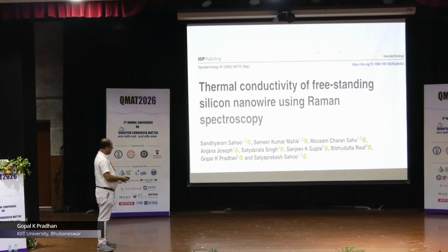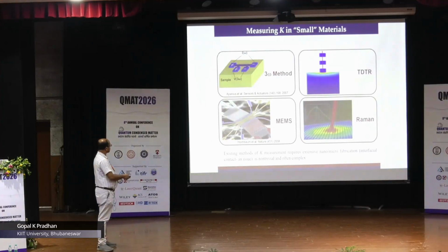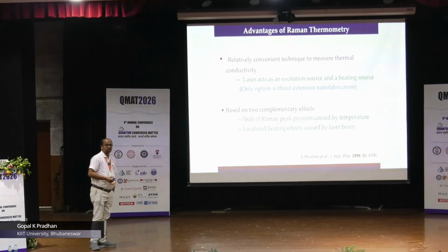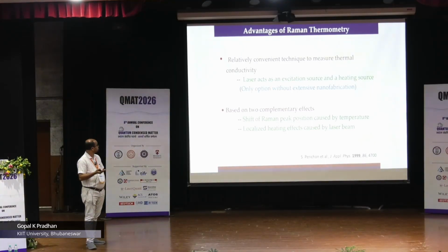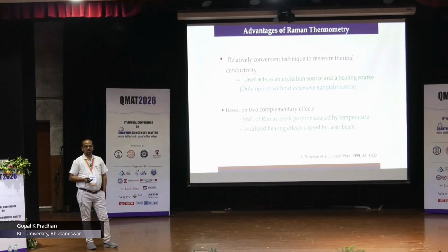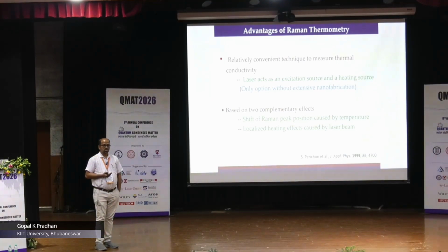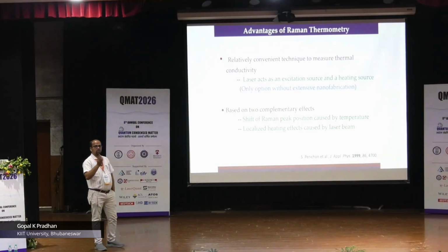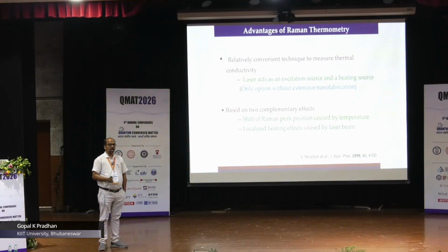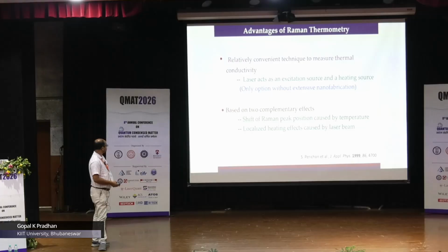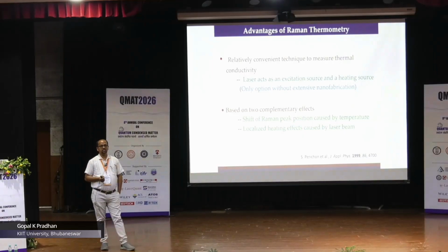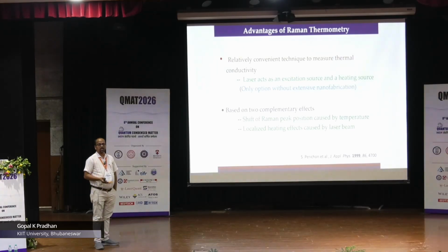So how does Raman help in this? This is like killing two birds with one stone. You have the same laser which is being used to collect the Raman spectrum, and the same laser is also being used as a heater. So you use the laser to heat up your sample, and you look at the phonon spectrum and see how it shifts as a function of either increasing laser power or increasing temperature. Once you know the temperature coefficient or the power coefficient of the Raman shift, that is d omega by dT or d omega by dP, you can model your heat transport and calculate the thermal conductivity.